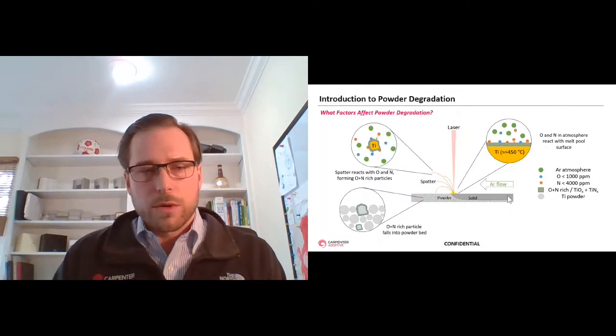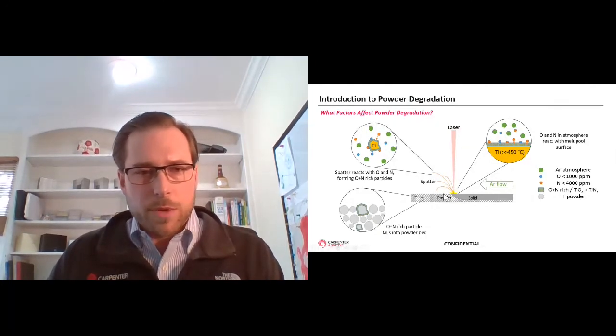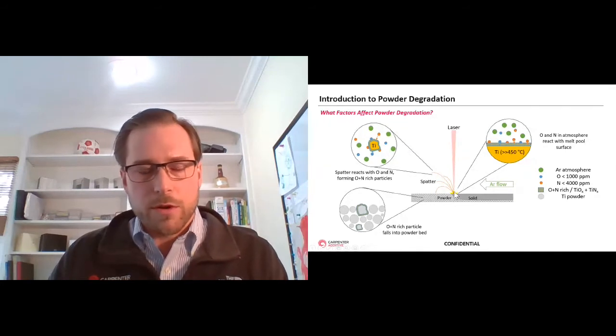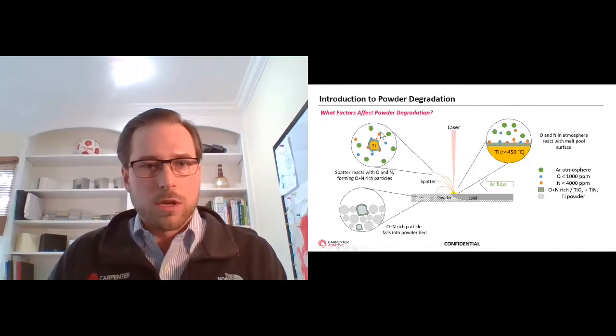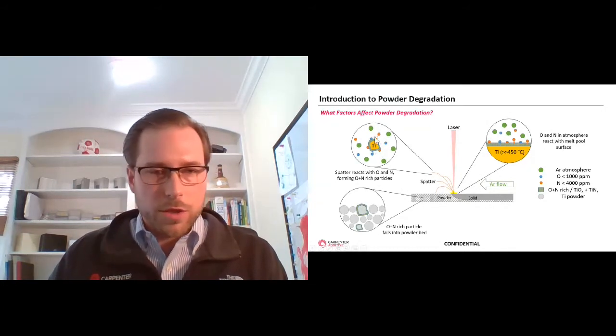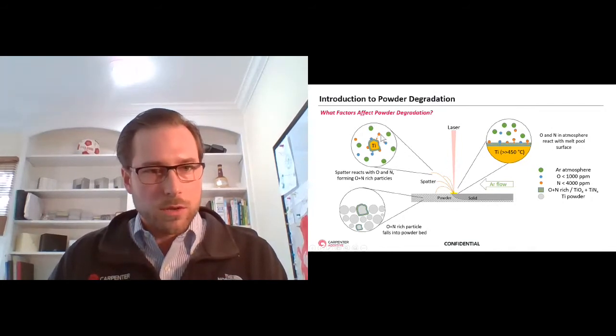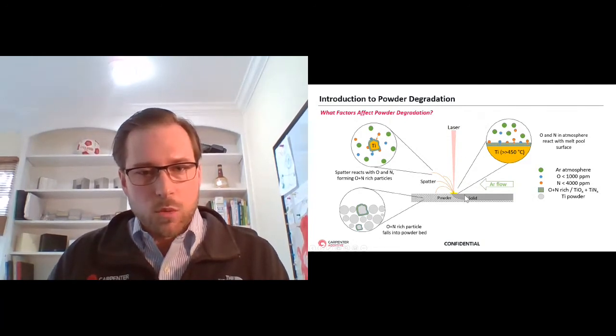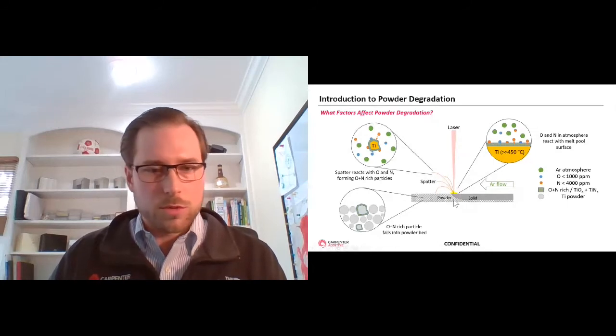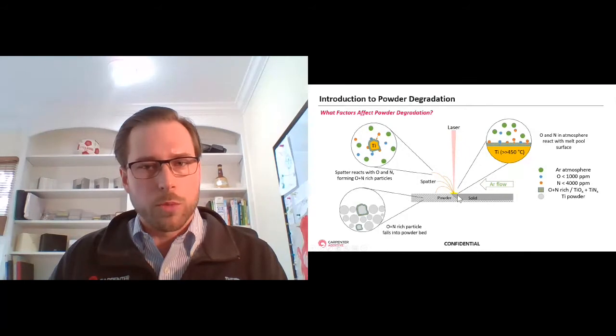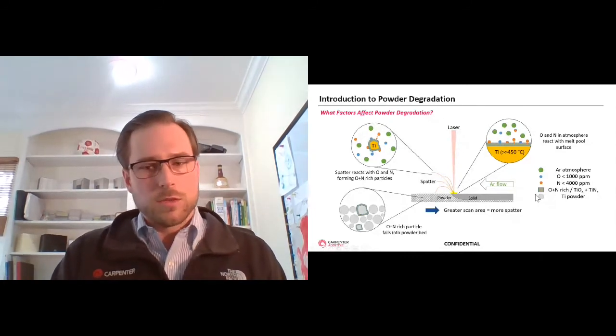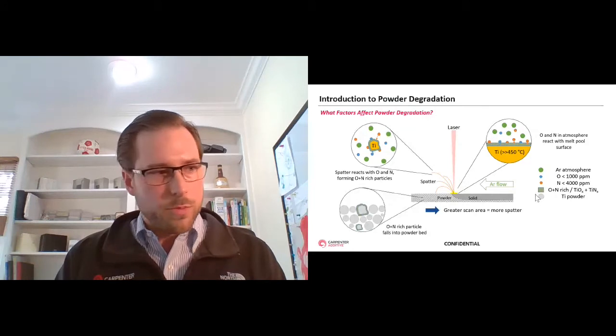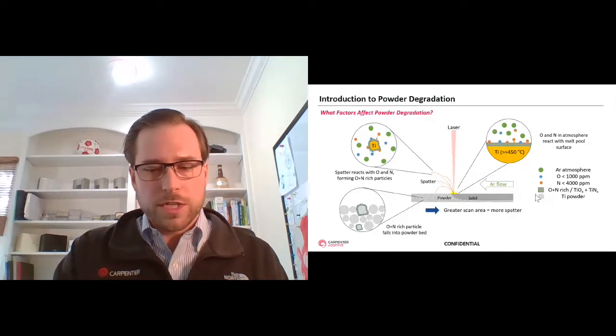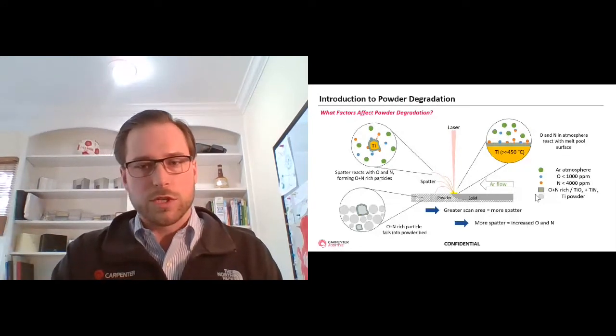One of the things that we see is that as the laser is forming the melt pool, you're having these particles ejected out, and it's either molten particles ejecting out, which are absorbing oxygen and nitrogen, other gases onto the surface, because when they're molten, they absorb at a higher rate, and landing back in the powder bed. What we also have is the melt pool itself at temperature is more susceptible to absorbing oxygen. So we see an increase in parts with laser. And the reality of it is when we talk about reuses, that's not really a great measurement, because as you increase the scan area, you have more spatter. If you have more spatter, you increase your oxygen and nitrogen.